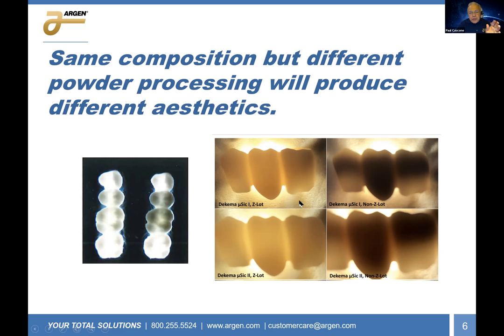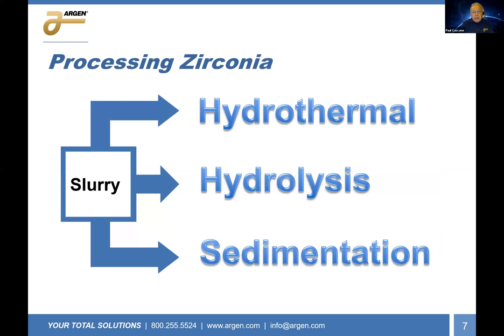And here are the bridges made from those, with backlighting. And you can see that the large grain one is much better than the fine grain one with regard to translucency. So my point now, and for the balance of my portion of the talk, is that the composition alone of zirconia does not determine how well the material is going to behave. It does not determine the overall strength, and it does not determine the overall translucency and how well the material can reproduce a shade. That is determined not only by the composition, but also by the processing. The processing is more critical with zirconia than it is with other prosthetic materials that we've used in the past.